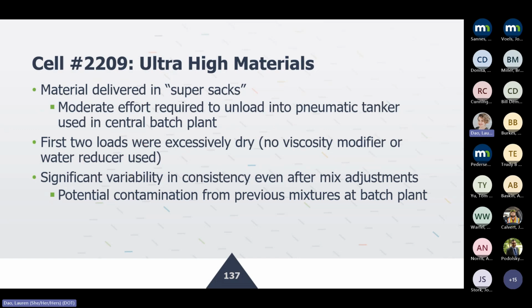These are huge bags, 2,000-pound bags that are not really convenient for moving. Especially if you have some blended material, 2 or 3 powders that have been blended together. We saw that for some of the materials it was not really a homogeneous mixture, so that might also have resulted in some mixing issues. But these super sacks were transferred into a pneumatic tanker that was used in the central batch plant, and that is not ideal. It was quite a process, as it was mentioned to us.